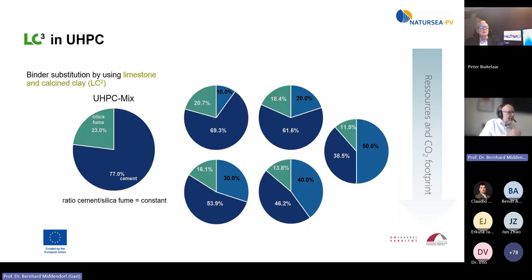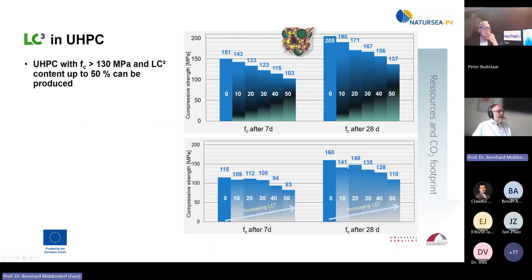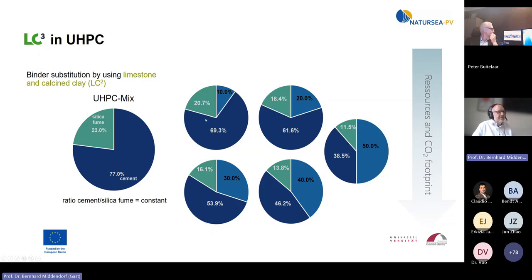What I have done once is, sorry, I did not use LC3 in UHPC, because LC3 means you have limestone, calcined clay, and some others. I used a normal UHPC mix, Z1, 77% cement, 23% silica fume, and then I substituted LC2. That means only limestone and calcined clay, 10%, 20, 30, 40, 50. And then I looked at the compressive strengths after 7 and 28 days. The first one was without substitution, and after 28 days 205 megapascal. When I substitute 10, 20, 30, 40, 50, you see that is only 50% Portland cement in it. All the others are limestone and calcined clay mixed up to 50%.